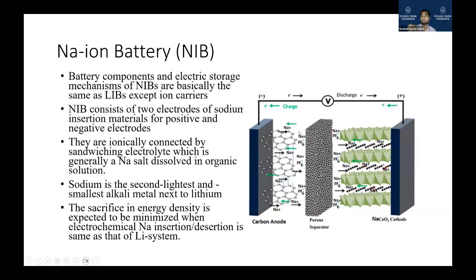But the thing is, sodium ion is a little bit higher in size than lithium ion, right? Because we can see that lithium is above sodium, and after lithium comes sodium. Sodium has atomic number 11. So this time the separator needs to be more porous, and the pore size should be higher than the lithium ion battery, because now the traveling ion is sodium, and it is higher in size than lithium. So when we are charging the battery, the sodium ion from this cathode is actually traveling through this porous separator and going to this sodium, actually it's a carbon anode, and then it has a sodium cobalt oxide cathode.